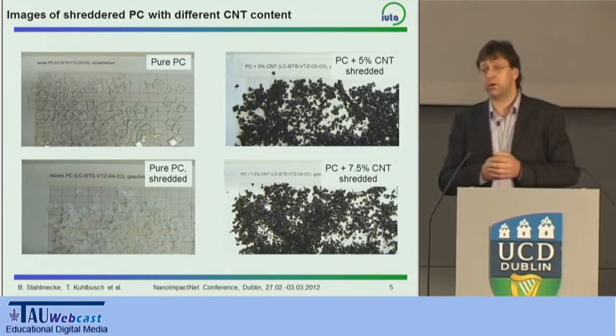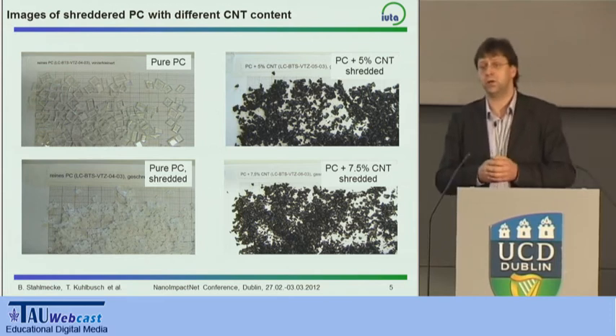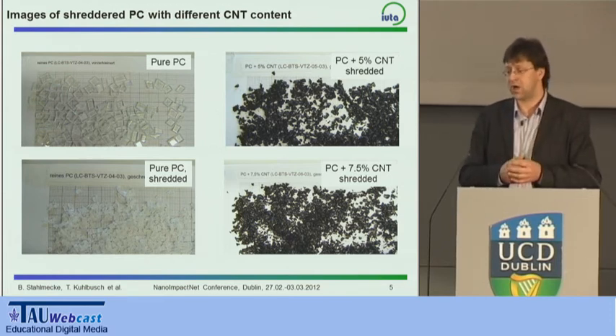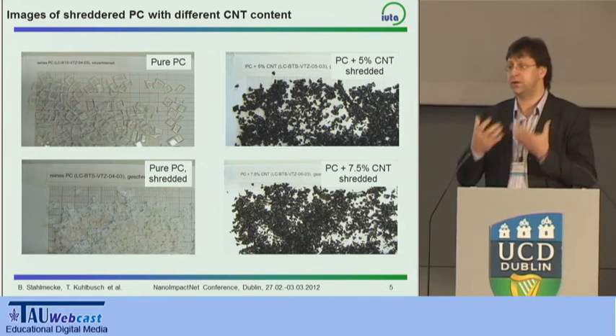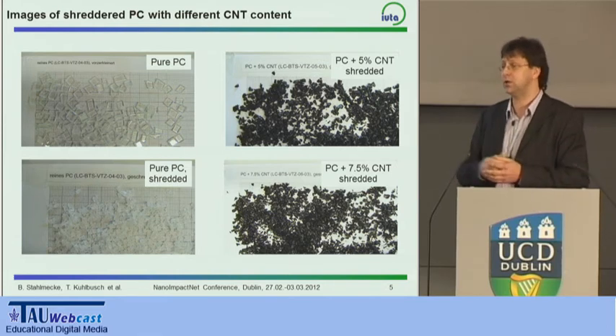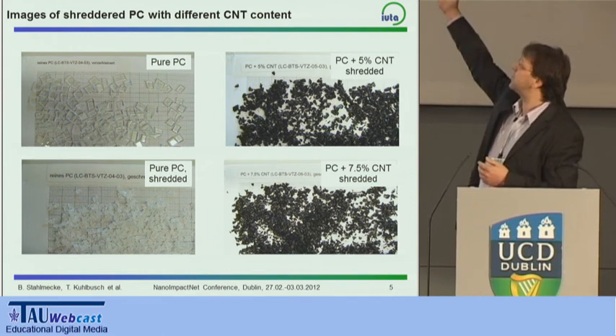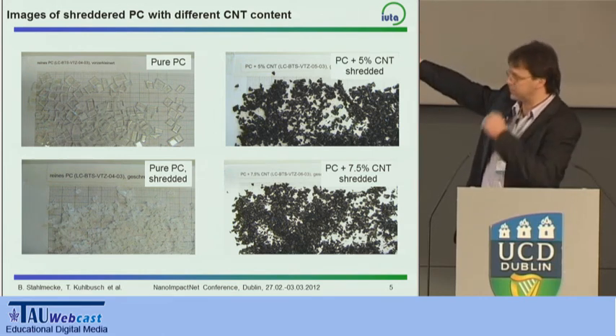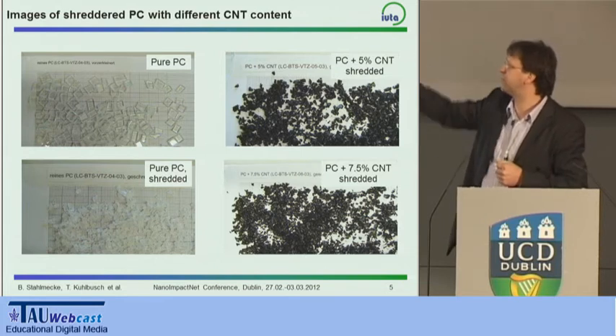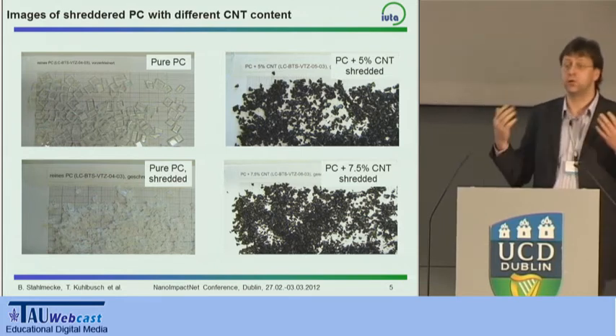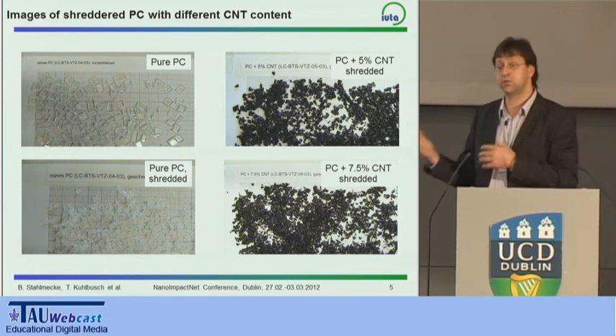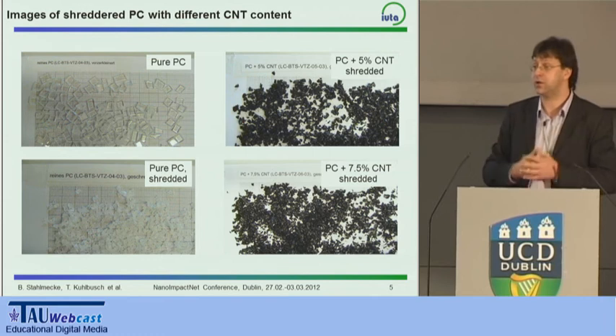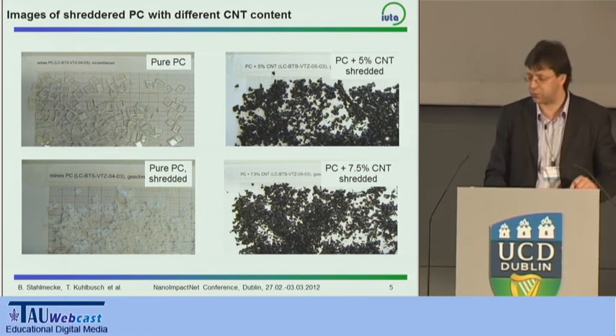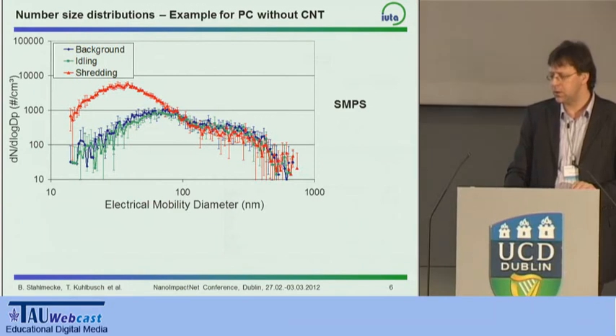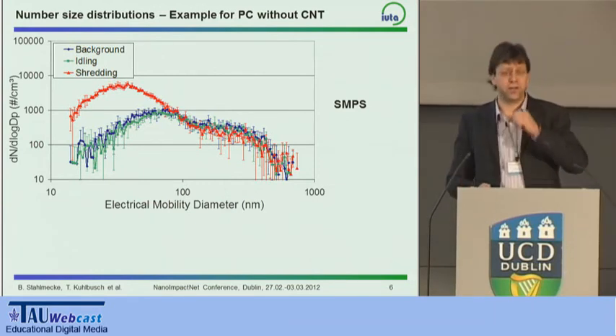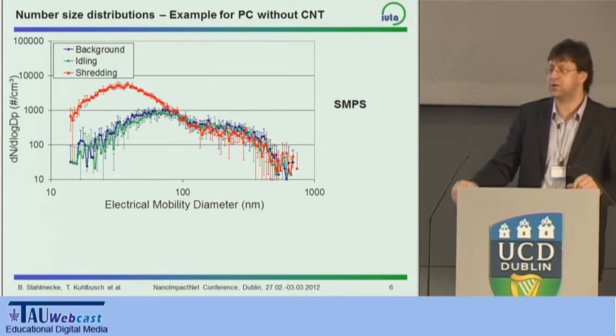So this is just a picture of how it looks. At the upper left corner, you see the pure polycarbonate as it was fed into the shredding process. Then on the right side you see 5% carbon nanotubes, 7.5% carbon nanotubes, and the pure polycarbonate without any carbon nanotubes as it looks after the shredding process. There are some smaller fractions and some larger fractions of the particles that can be observed. The basic results we obtained are shown here for the SMPS size range.